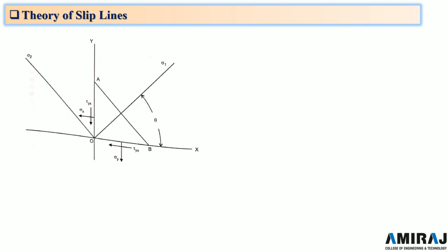Now if we take the direction of maximum shear as the coordinate direction and transform the equations along this direction, these equations will get converted into algebraic equations, and this is in tune with the general properties of hyperbolic partial differential equations. So let us discuss that.